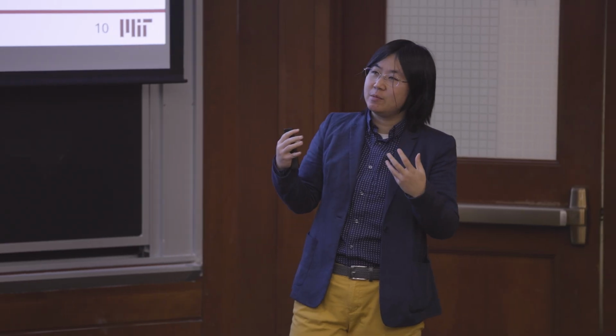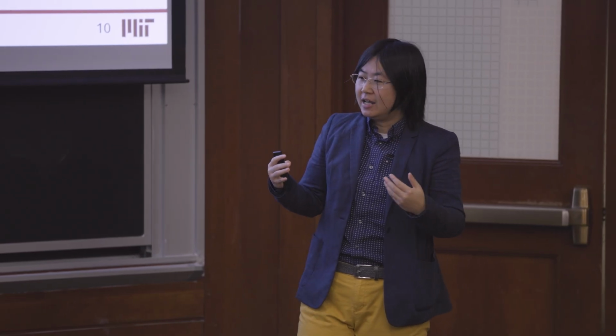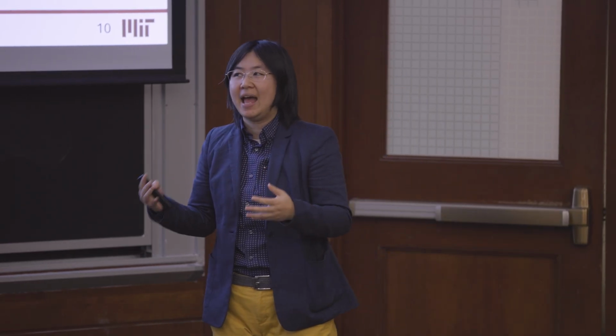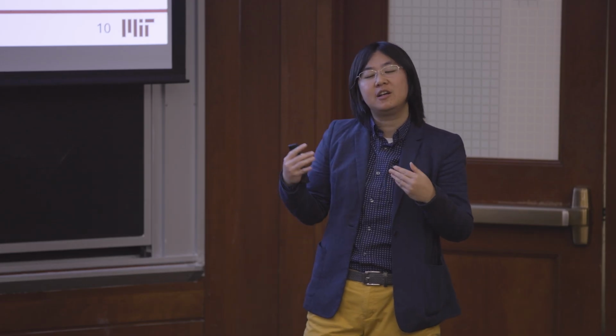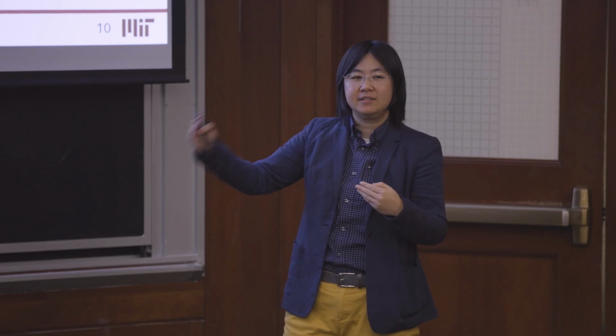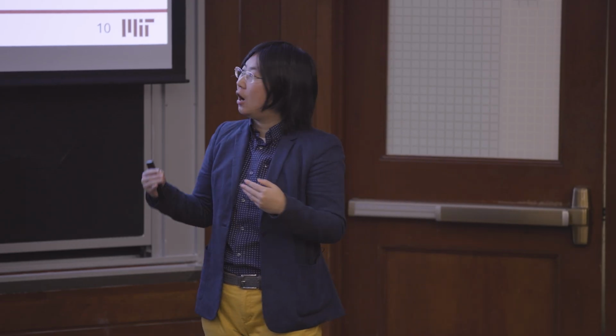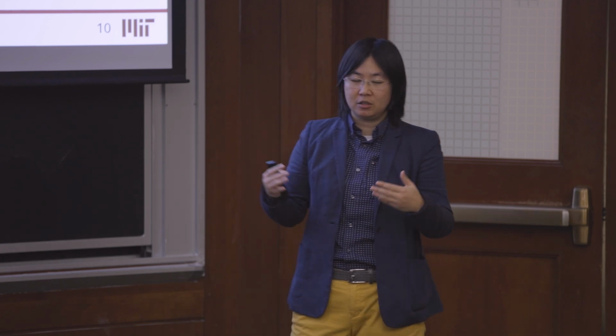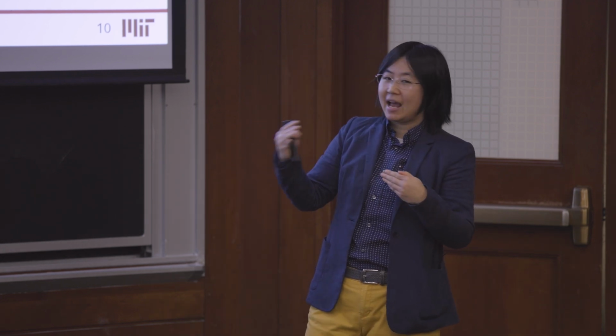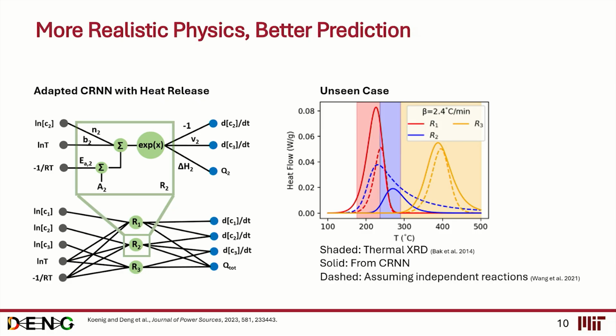And why it's so important to have a physical model is that if we do a pure data-driven model without any physical prior, we will not be confident about applying it to an unseen case. However, now that we have the physical model and everything's transparent, we can explore what would happen for unseen cases. And this is exactly what I'm showing you on the slide. The dashed lines from the literature that you previously saw managed to fit a 2-peak curve, however, it's unphysical.